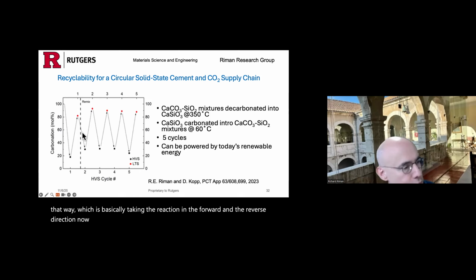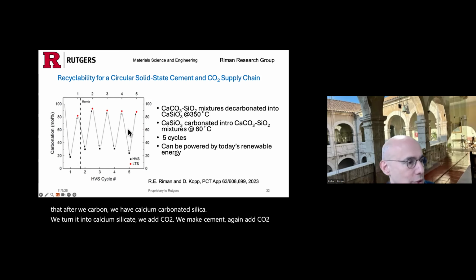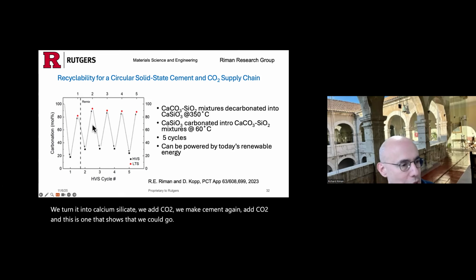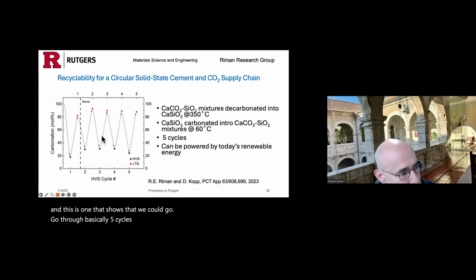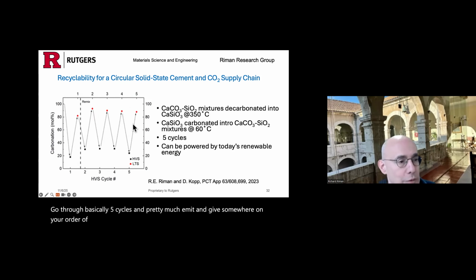Now, this was one of the first results we got, which basically showed that after we have calcium carbonate and silica, we turn it into calcium silicate, we add CO2, we make cement again, add CO2, and this is one that shows that we could go through basically 5 cycles and pretty much emit and give somewhere in the order of about 60% of the CO2 when cycling it. Likely we'll be able to do much better than this.